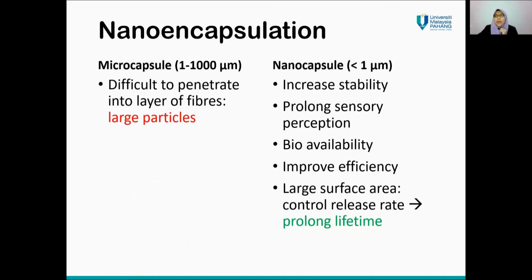Okay. So aroma capsules can be divided into microcapsules, size range from 1 to 1000 micrometer, and nanocapsules, size less than 1 micrometer. So far, most of the reports focus on the preparation of micro-sized aroma capsules. However, microcapsules are difficult to penetrate into the layer of fibers due to their large particle size, which limits the use of microcapsules to finish micrometer fabric fibers. So then, nanoencapsulation is introduced, and it represents an efficient alternative in increasing their stabilities, prolong sensory perception, bioavailability, and improve their efficiency. The large surface area provided by nanocapsules is appropriate for incorporating aroma compounds and prolong their lifetime by controlling the release rate.